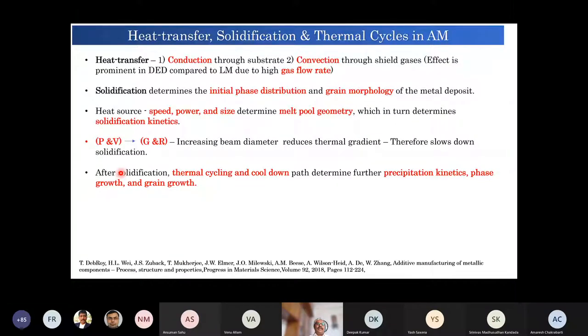Well, I have already told about the importance of heat transfer, because heat transfer can take place through conduction, through the substrate, and convection, through shielded gases, and the latter effect is more prominent in DED compared to laser melted processes or powder bed processes due to high gas flow rate. Solidification also determines initial phase distribution and grain morphology. Heat source decides the speed, power, and size that ultimately influences melt pool geometry, which determines solidification kinetics. And then we have the G and R parameters, as we have discussed, and they control the solidification process, and of course the microstructural aspect of it.